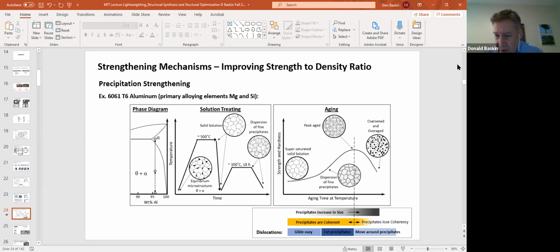When you have a coherent precipitate, in order for a dislocation to move through that precipitate, it has to cut that precipitate in half. That requires a lot of energy. Because of thermodynamics and the extra energy associated with having this interface between the precipitate and the base material, the aluminum, there is a driving force for these precipitates to grow with time.